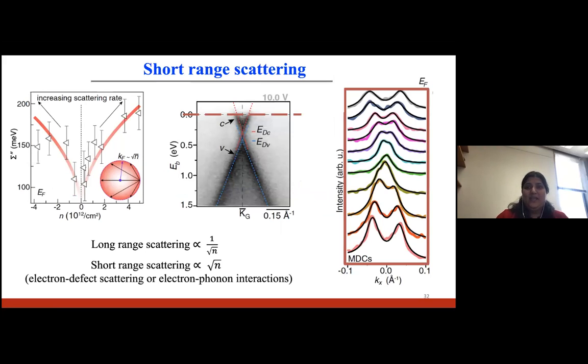Next, we can also look at the doping dependence of the imaginary part of the self-energy, which I'm plotting here. We can extract this from the line widths of the Lorentzian fits to the MDCs at the Fermi level. What we observe is that this imaginary part of the self-energy is suppressed near the charge neutrality point. Then it increases for both N doping and P doping, and it follows this square root of N dependence. This is consistent with short range scattering.